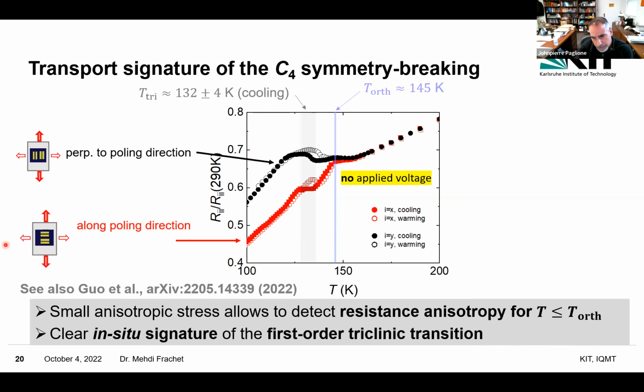The other comment was about the phosphorus substitution. It is true, right, that you can make the pure phosphorus compound? Actually that is a 3 Kelvin superconductor? Yes, exactly. It's interesting that the 3 Kelvin superconductivity suddenly jumps, but there's not much change through the phase diagram in that regime. I think that's really the main difference with what you have done with strontium. What we have above the suppression of the triclinic phase is really a flat Tc compared to what you have.